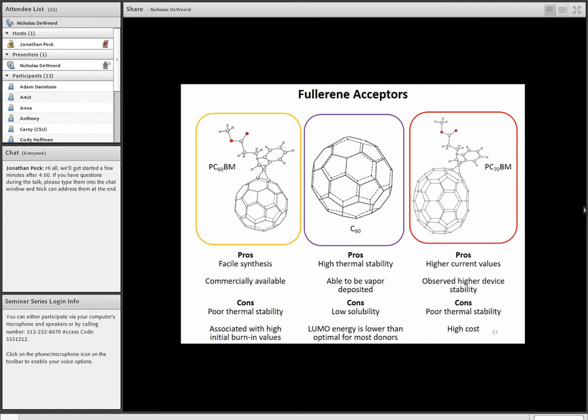Lastly, PC70BM, like I said, if you're testing a new donor, it's pretty common in the literature to test it against PC70BM, and that's primarily because it usually shows higher efficiency devices. It usually has a higher JSC or current value, and has been shown to have higher device stability. But PC70BM, specifically that C70, is more expensive than C60.